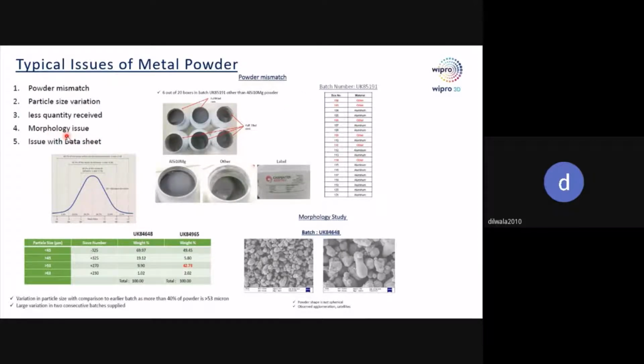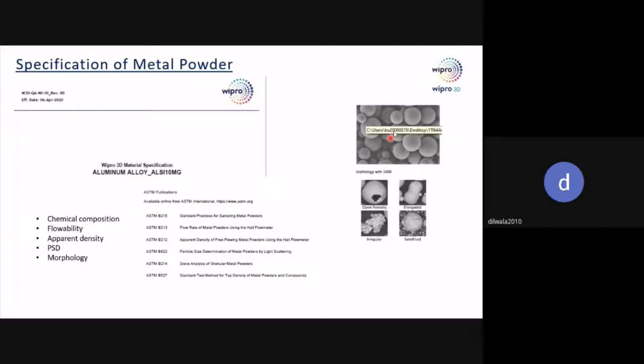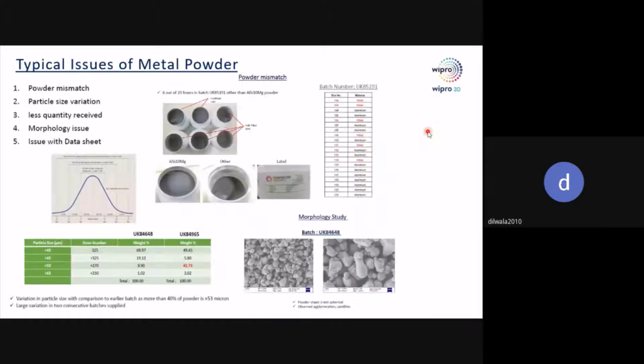Then comes microscopy. If you look here, this is how we expect the powder particles to be, spherical in shape. But if you look at the powder in this lot, some have satellite structure, some are irregular in shape, some are elongated. So these are different types of issues that arise in morphology. The problem here is, let us assume we have an elongated particle. When we are melting, this end of the particle gets melted and this will be projecting on the outer surface of the part, which will affect our surface finish or have other effects.